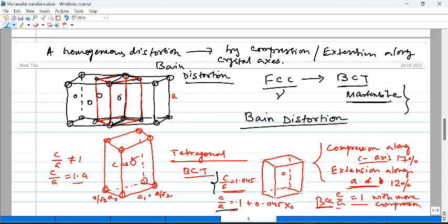Do you remember when we discussed the crystal structure of these iron carbon alloys, the austenite and the ferrite? We discussed where the carbon actually sits, isn't it? We know where the carbon is located. It is basically the octahedral voids, right, where the carbon would sit. Where are the voids in the FCC lattice? It is at the body center and the center of the edges.